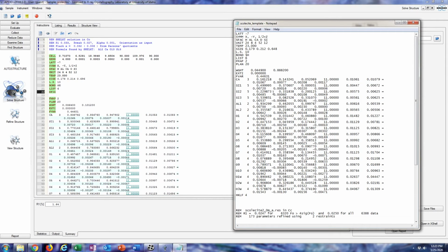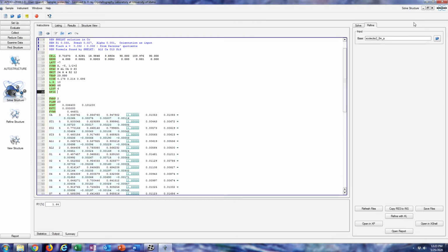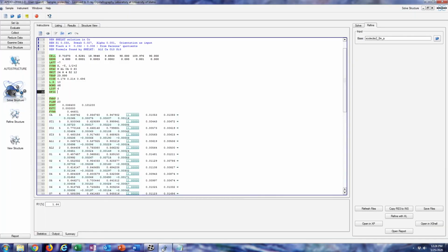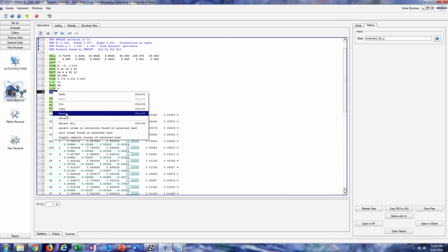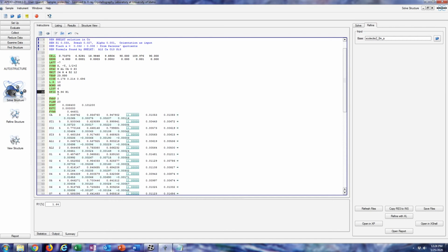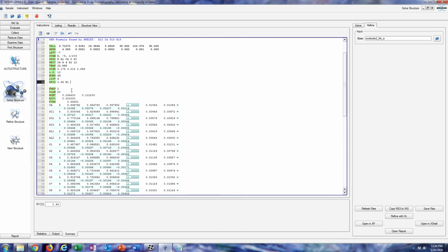I'm just going to use the default standard deviation. So all I have to list is DFIX, then the bond length, which is 0.96, and then enter the atom that the hydrogen is bonded to and the hydrogen itself. Just to remember, this is what I did before. I'm just going to copy this. DFIX 0.96. It'll still probably be a little close to the oxygen, but that's okay. I'm fine with just using the regular standard deviation.